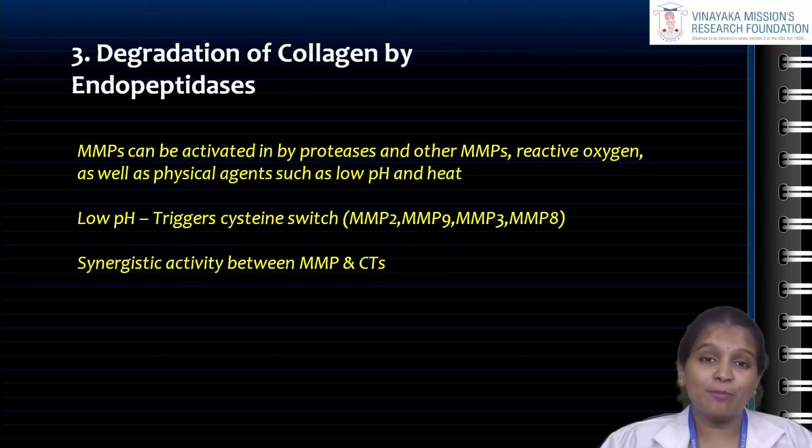And then the third and most important factor is the degradation of collagen by the endopeptidases. So I told you that the collagen is not completely encapsulated by the resin that is infiltrated. So ultimately the collagen is exposed, and the acid that enters when conditioning causes the activation of the fossilized endopeptidase proteases as well as the cysteine cathepsins. So these proteases and cysteine cathepsins remain fossilized within the dentin. So once the conditioning is done, it causes the exposure of these to the external environment, which further causes the degradation of the exposed collagen network.